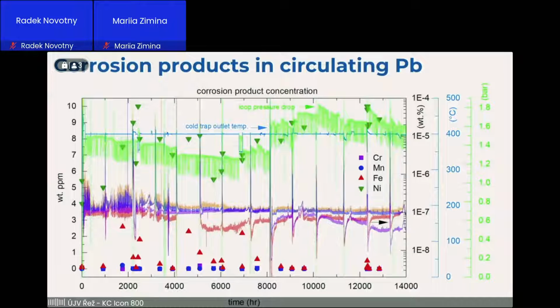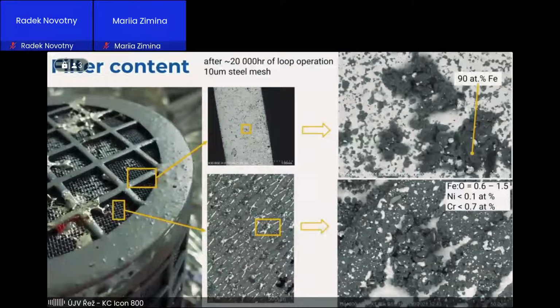We also did some analysis of the coolant during the exposure, and the main point is that there is no large-scale dissolution attack in the loop. Nickel is supposed to be the most abundant corrosion product because we have stainless steel specimens and a stainless steel loop. The majority of wetted surface contains nickel, and nickel is not there. In the filter content we have found lots of iron, but no nickel. Iron is not oxidized, which is a big surprise to us, and I think this free iron may be affecting the signal of oxygen sensors, and may be the reason that we are measuring lower oxygen content in the loop, and therefore there is a concentration of nickel in the surface of our spinel layers.